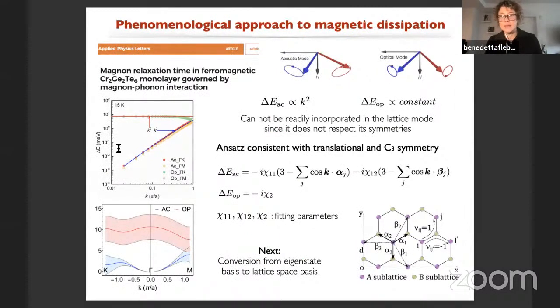So in this case, since we are considering a honeycomb system, we started going through the literature, and we saw that there was one work, an ab initio work, in which they looked at magnon-phonon driven dissipation. So they could calculate the band broadenings, the associated relaxation time of magnons in this ab initio simulation over the full Brillouin zone of the hexagonal lattice.